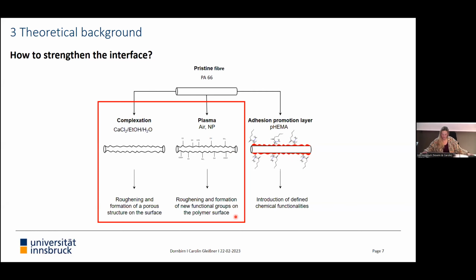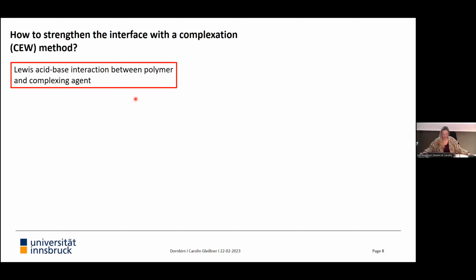But today I want to talk about the complexation-mediated solubilization method and the plasma method, and how they had an impact on the metallization and also on the interface stability. So how do I strengthen the interface using this complexation method? The abbreviation for this was CEW, so calcium chloride, ethanol, water. This technique is based on an acid-base interaction between the polymer and the complexing agent. As a reactant, you can use strong Lewis acids, like for instance aluminum chloride, gallium chloride, or calcium chloride.